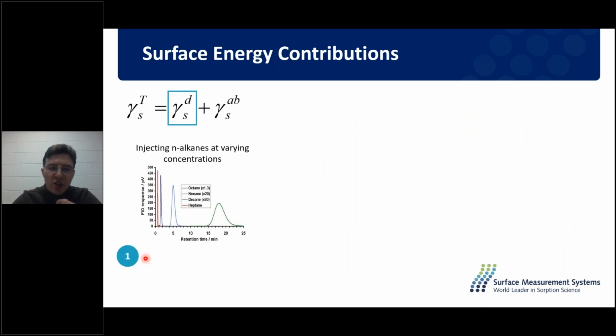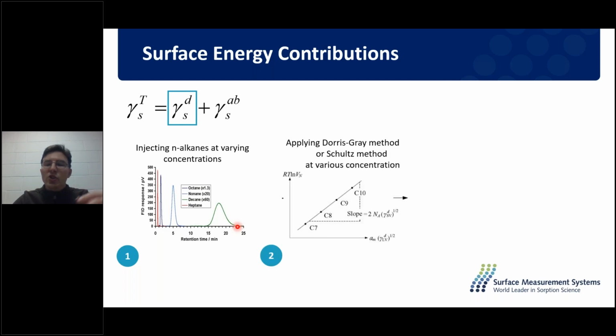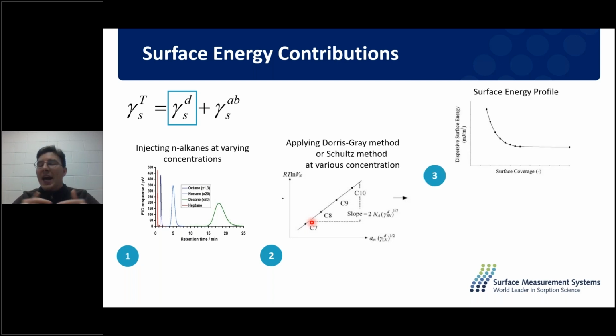So my dispersive surface energy, I will calculate that at a number of different probes. So here we can see I have injected heptane, octane, nonane, and decane. And we can see the larger probes are going to go through the slowest. Now, if I inject all of these probes aiming for the same surface coverage, so I've injected enough decane to cover 20% of the surface, I've injected enough heptane to cover 20% of the surface, then I can construct this, the alkane line. And it is from the gradient of this line that I get my dispersive surface energy at that specific coverage. Now, if I do this at a number of different coverages, I get a number of different energies.